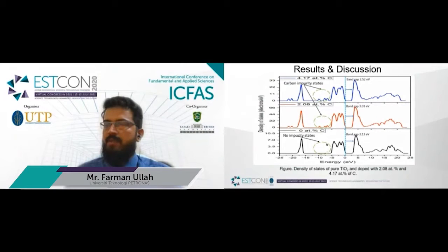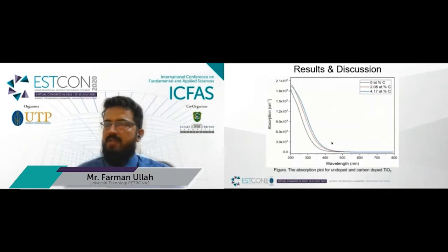These are the density of states plots for the pure and carbon doped TiO2 models. For pure TiO2 there are no carbon impurity states, but for the carbon doped TiO2 model the impurity states of carbon were introduced, displayed by this dashed line. The band gap was also reduced from 3.13 to 2.52 electron volt for carbon doped TiO2. The density of states results also confirm the band structure results. The optical absorption plot for undoped and carbon doped TiO2 is also shown in this figure.